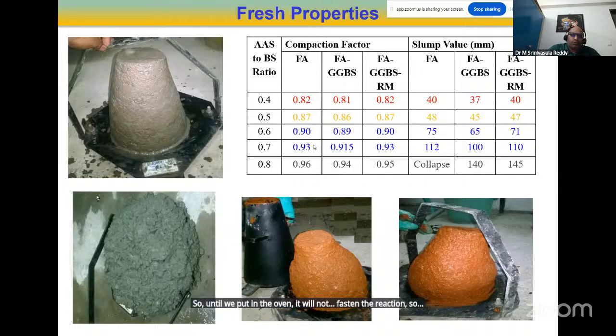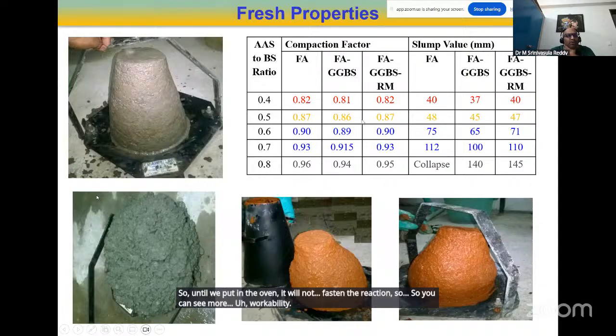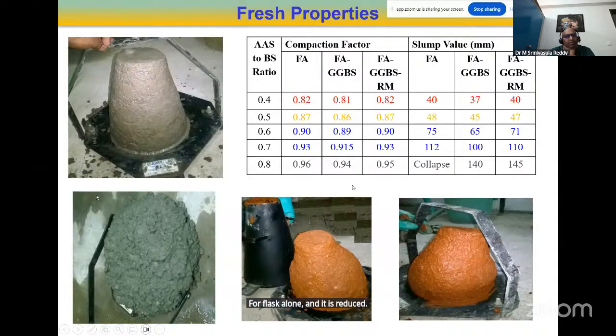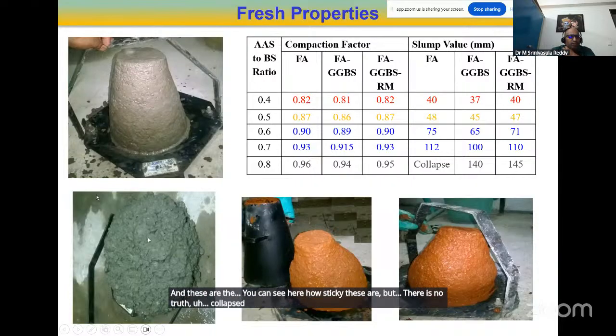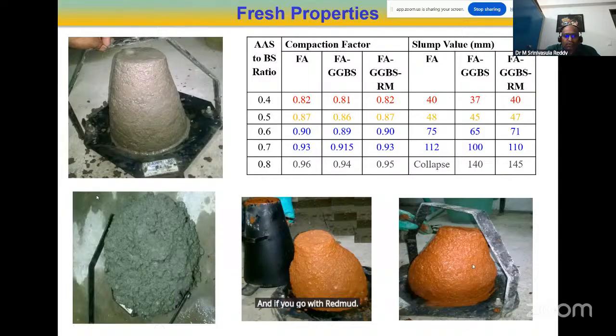So you can see more workability for fly ash alone, and it is reduced with fly ash and GGBS. The slump also shows the same thing. And you can see here how sticky these are, but there is no true collapse type of structure. We can only observe collapse when we go with 0.8 or 0.7 for fly ash alone. And if you go with red mud and GGBS, it will be sticky, even though it gives good workability with increase in the AS to BS ratio.